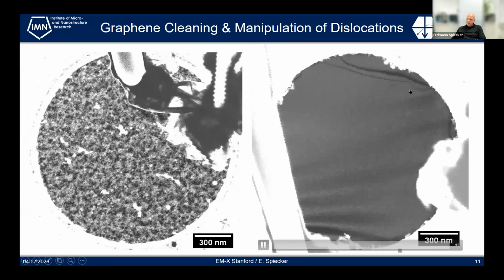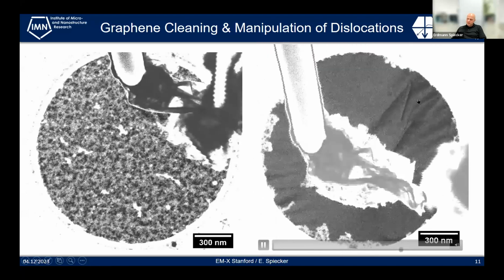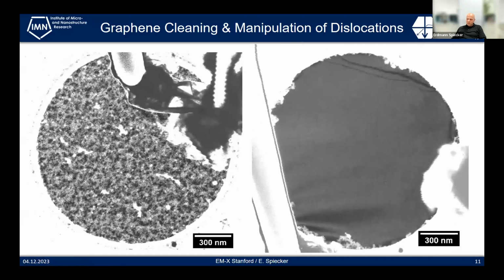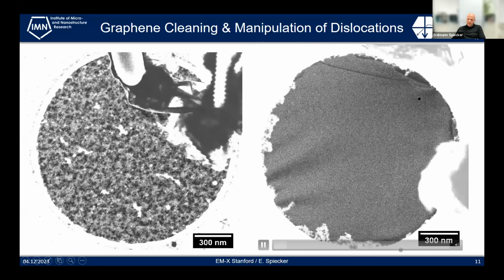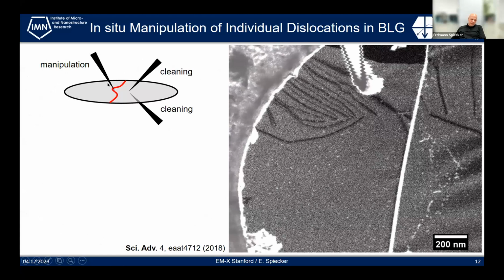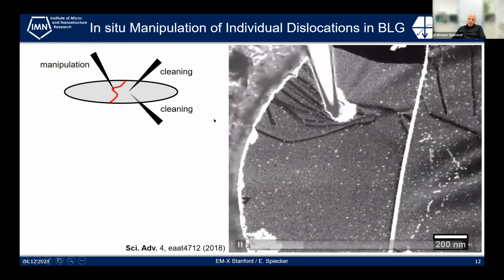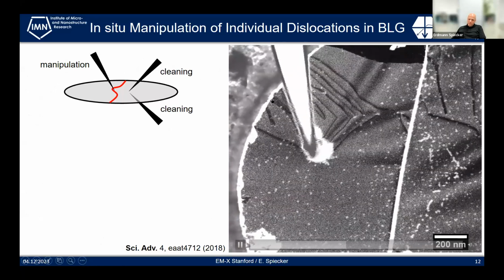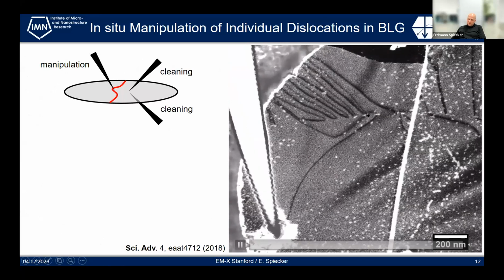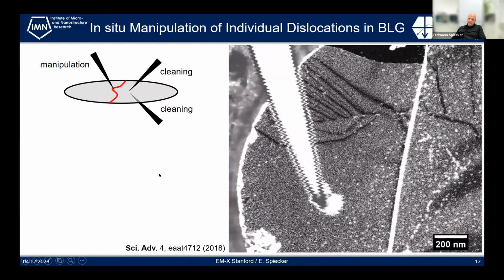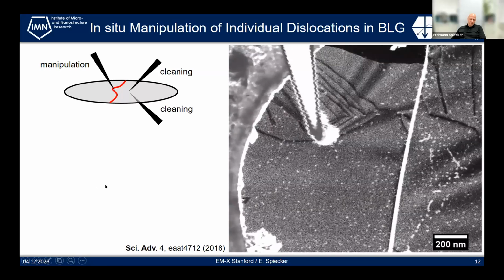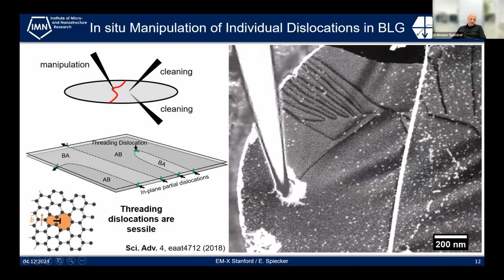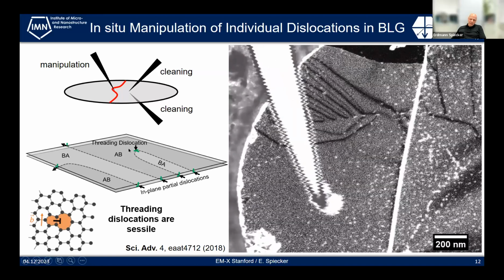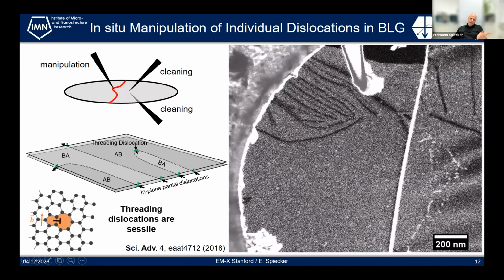So you see anchor points. These are threading dislocations where the dislocation goes through one of the top or bottom layer, but you can really explore now the properties of dislocation, like in this particular case, the line tension. And we extended our approach by introducing a third manipulator, two for cleaning and then one for manipulation. And then you can play with the dislocations with a guitar. So these are dislocations which are anchored at so-called threading dislocations, and you can individually draw them across the graphene. And you can analyze all that in detail, and we could show that actually the anchor points which are sessile are these threading dislocations penetrating to one layer, and there it's a normal dislocation in monolayer graphene.